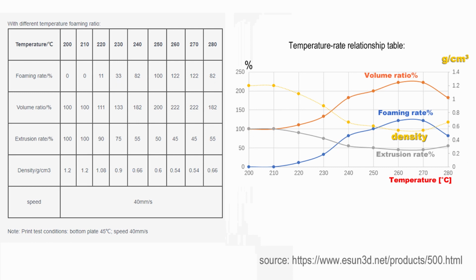And from this table I can see the lowest density I can get if I print it between 260 to 270 degrees Celsius. In this case the extrusion rate has to be only 45%, and the density will be approximately 0.54 grams per cubic centimeters. And I believe that this information is also very important, that the speed must be approximately 40 millimeters per second, because it needs time for this foam to be created.